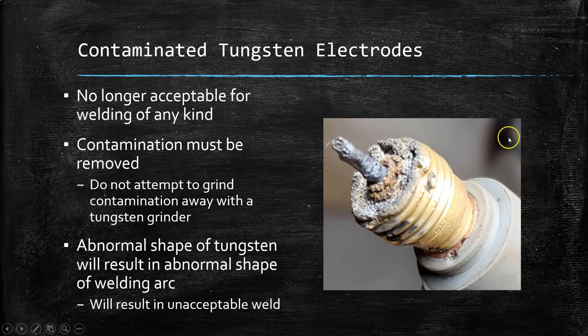Now, just to rewind a little bit, when we talk about removing contamination, I don't mean just grinding the contamination away. You need to completely remove the contaminated portion of your tungsten, either by cutting it off or breaking it off. Do not just stick it into a grinder and hope that you'll remove all of it and start fresh with a ground tungsten electrode.